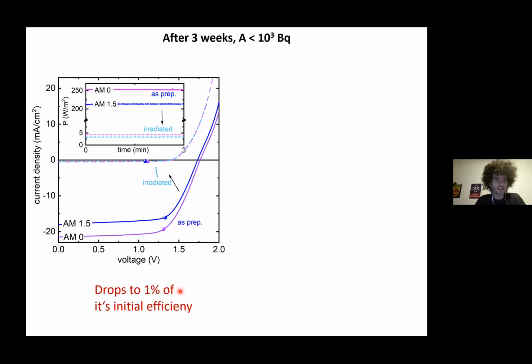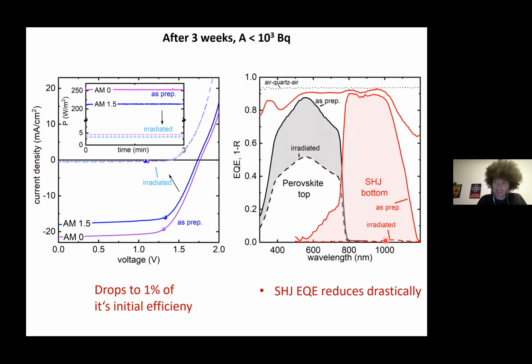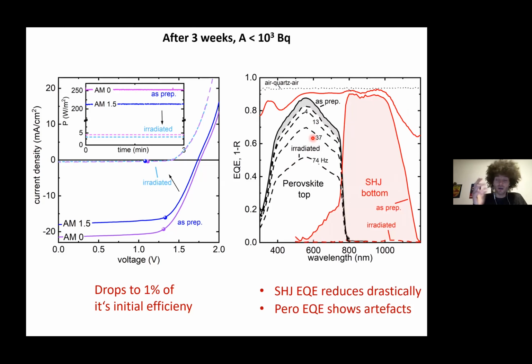All right. So the reason behind this degradation basically is that the silicon subcell degrades rapidly. And here the dashed line is measured after proton irradiation. But we also see some damage in the perovskite subcell. Interestingly, this damage, or this EQE, was really affected by a lot of artifacts while measuring. I'm still not 100% understanding those. However, under the right measurement conditions, we could almost recover that perovskite quantum efficiency here. So we think that the perovskite was not damaged and only the silicon.